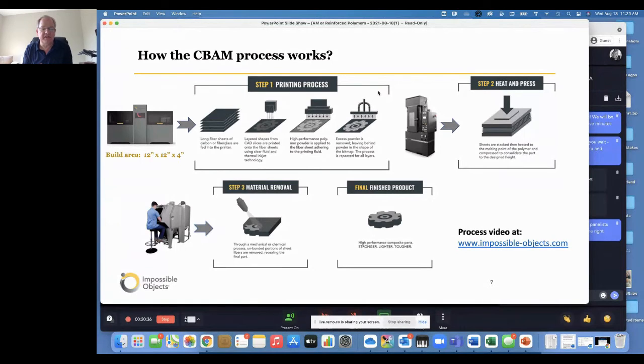The second step is that those sheets are transferred into a heated press and taken up to the melt point of either the thermoplastic or thermoset material. Once you reach that melt point, for PEEK, it's about 380 degrees C. For nylons, it's about 200 degrees C, and for the thermosets, it's about 185 degrees C. Once you reach those set points, we press the sheets together, and that's where you're forming your thermoplastic or thermoset composite parts. At the end of the pressing process, we go to the final step into a removal cabinet and remove the unfused fibers from the build block to get your finished part. Fiber volume content for this particular process is about 25%, and that's how the process works. We can go on to the next slide, please.